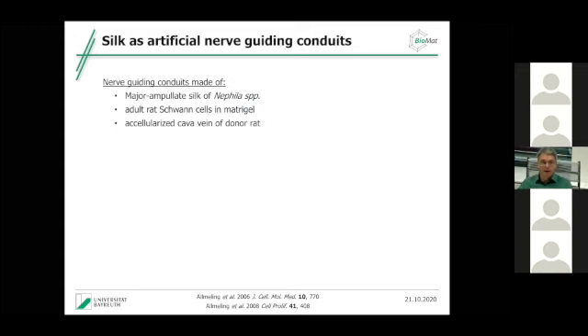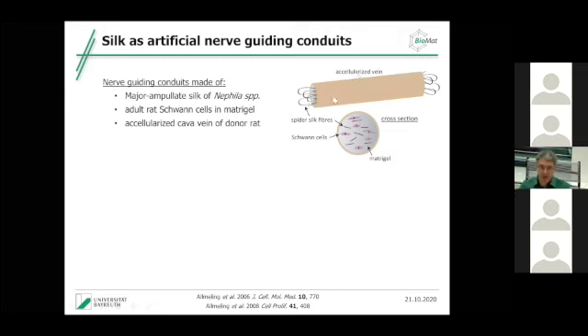Therefore, a group at the medical university in Hanover started to use spider silk, and they took spider silk from spiders. Yeah, so major ampullate silk fibers from spiders. These were supposed to be guiding structures for the nerve cells. Then they embedded this in matrigel. Matrigel is a gelatin hydrogel where they implemented Schwann cells. And then they put this whole thing in a vena cava of a donor rat. So they removed all the cells from the vein, and then they put the spider silk fibers and this matrigel inside. So that was the setup. That's the vein. These are the spider silk fibers, and here in between you see the matrix of matrigel.